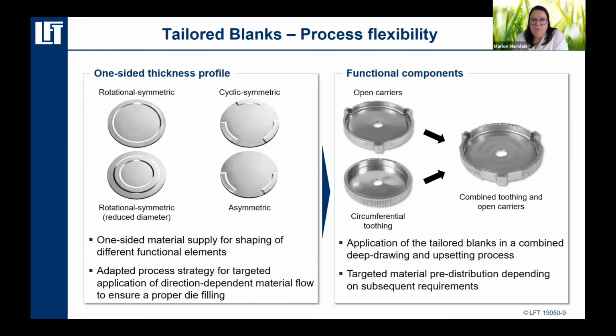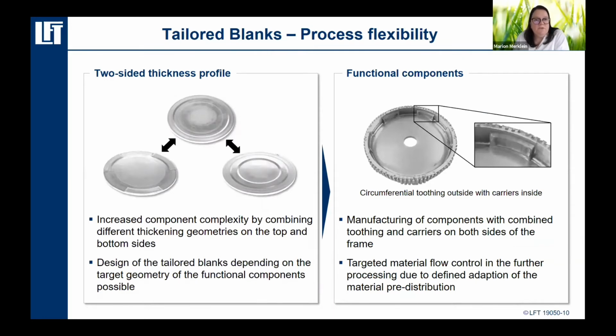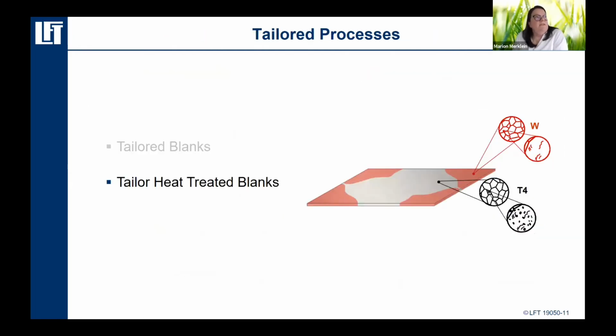For example, the geometries, as I mentioned before, such as what we call a circumferential toothing. We can also produce open carriers and improve the formability. Or if we take a look at the next slide, we can see that it is also possible to have such a thickening operation, and so a flexibilisation of the material on both sides of the sheet metal. And if we do so, we can also add, for example, such inner elements for such carriers, internal carriers, which are necessary for the load capacity of the component. And so we can combine nearly any idea of thickening in order to improve the forming behavior and also the function of the component afterwards. And of course, that is especially important for steels. I can really say that's the most effective way to improve and flexibilize the formability of steels.